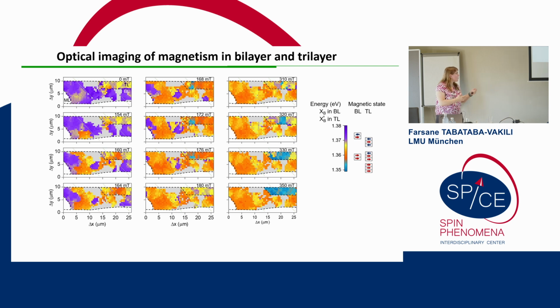And here, I'm showing a larger sample region and all of these transitions. So we start off with this entire sample region being antiferromagnetic. The gray regions are areas where we have bubbles and other stuff where we can't really determine the exciton energy. And so, as we increase the magnetic field, we see here the ferromagnetic domain in the bilayer nucleates here at the bottom. It takes around 30 millitesla for this entire bilayer region to become fully ferromagnetic.